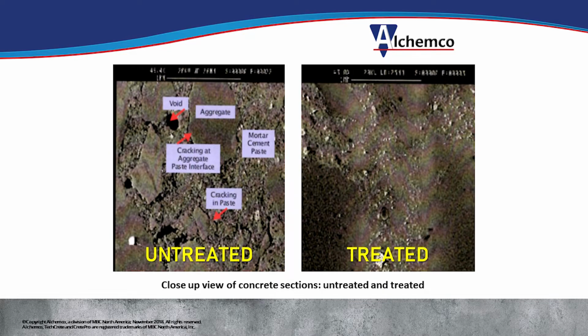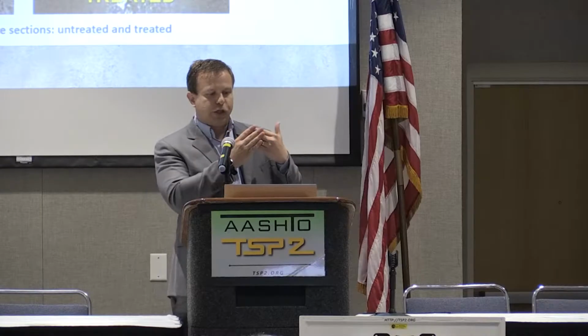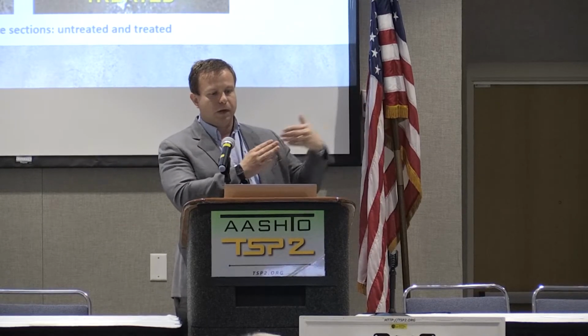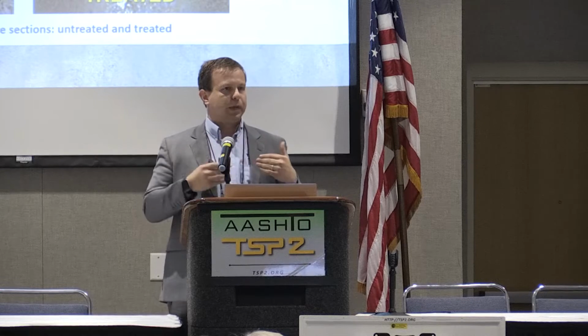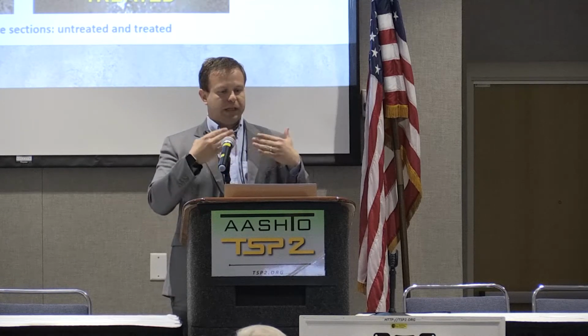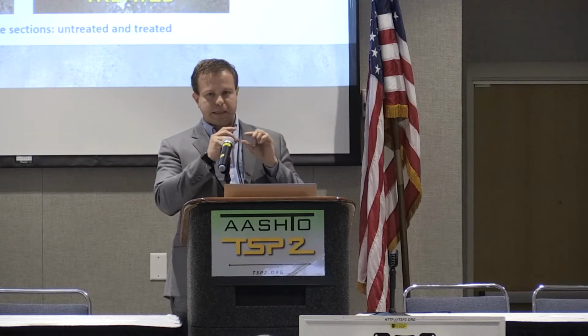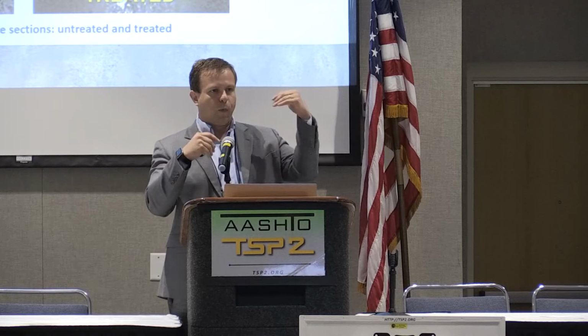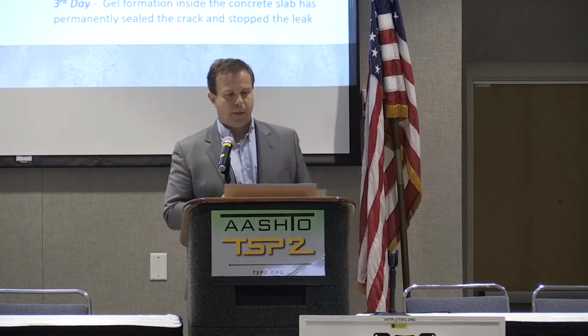And here we see the untreated side compared with the treated side. On the untreated side, we're able to see the voids and the cracks. And then after you spray the product, the gel that we saw a couple of slides ago, that's exactly what we're seeing here on the treated side. So this material is going to form this subsurface barrier where water is not going to be able to penetrate.